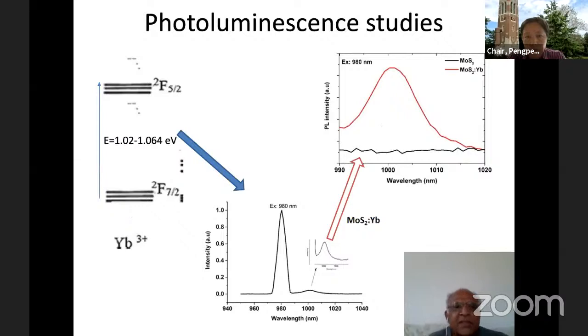Final couple of slides. This is the room temperature PL analysis. As you know, we have doped this film with ytterbium. Ytterbium has only two levels. The upper state is separated from the ground state with an energy gap of around 1 electron volt. And because this is around 1 electron volt, we can use a 980 nanometer laser to excite ytterbium ions. And that's the 980 nanometer peak you can see in the PL, and you can see the emission